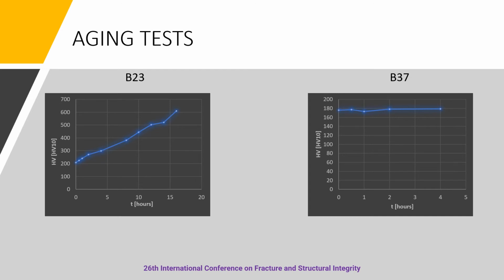Since this kind of alloy is known for its good aging properties, both the alloys were subjected to an aging test at 550 degrees Celsius after being solubilized at 900 degrees Celsius. These two graphs show the Vickers hardness test at different aging durations. While the hardness of B37 is more or less constant after a few hours of aging, it is B23 that becomes interesting, as it can be seen from the graph of B23 that there is a sharp and substantial increase in its hardness with respect to aging duration.